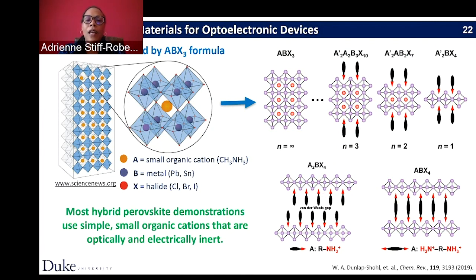A lot of the work that's been done with these perovskites has been on three-dimensional bulk perovskites, where you have a small organic molecule in this inorganic framework. And people make these materials very well with solution processes. You don't need MAPLE to make these materials. Where MAPLE comes in is that there's a lot of effort to replace some of the small molecules with a larger organic molecule. And when you do that, you can start to really change the properties of the material. The smaller organic molecules just keep the structure together. They're inert.